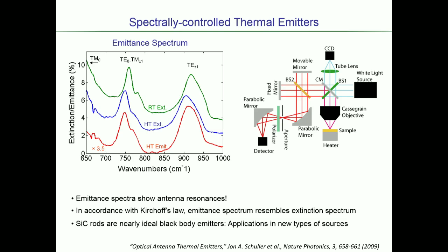And if I heat it up, then that's the red spectrum. I can actually obtain thermal emission from these Mie resonances. So by having high-index nanostructures that show optical resonances, by heating them up, I can thermally emit just in these resonances, and you use the resonant properties of these whiskers to control at what frequency I emit thermally, and also in what directions I will emit thermally.